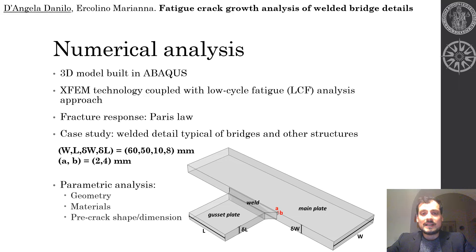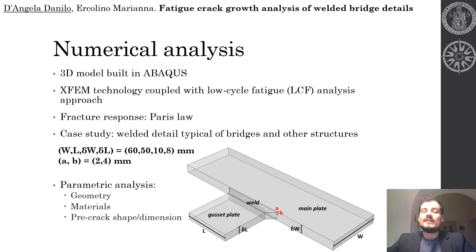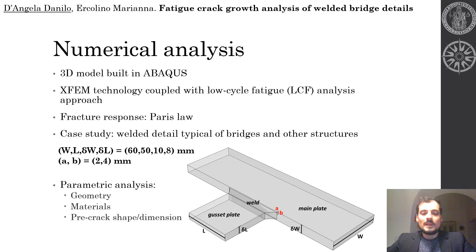We performed numerical analysis in order to assess the fatigue life of welded bridge details. We built three-dimensional models in Abaqus by coupling XFEM technology and a low cycle fatigue analysis approach. The fracture response was implemented according to the Paris law.